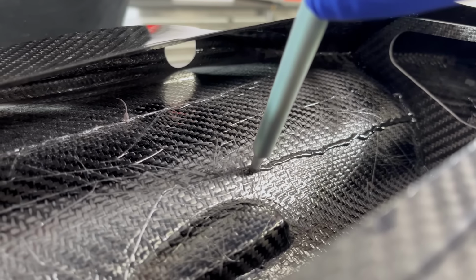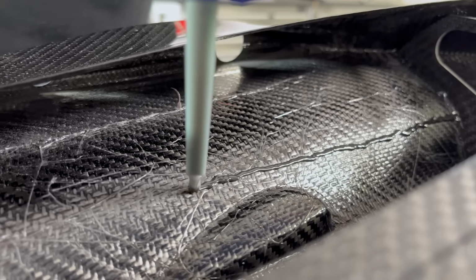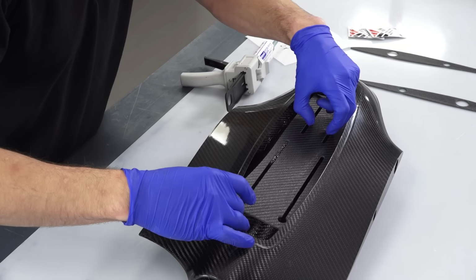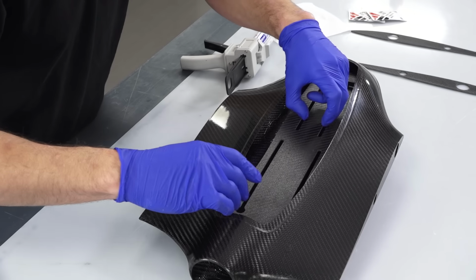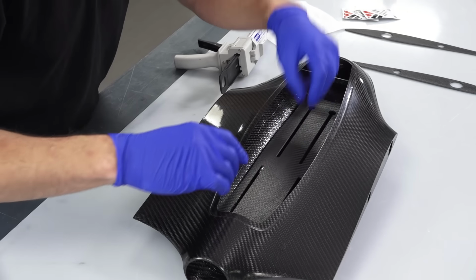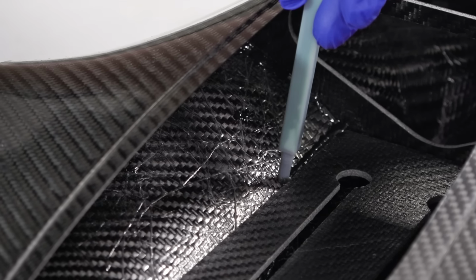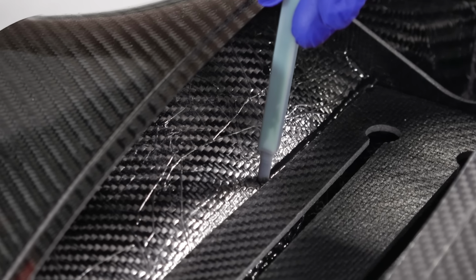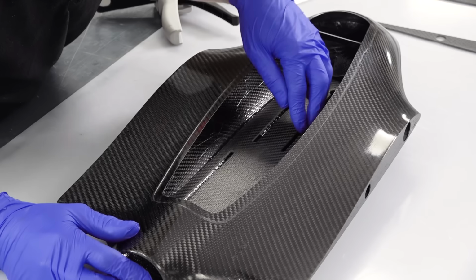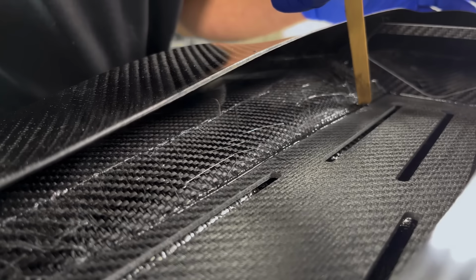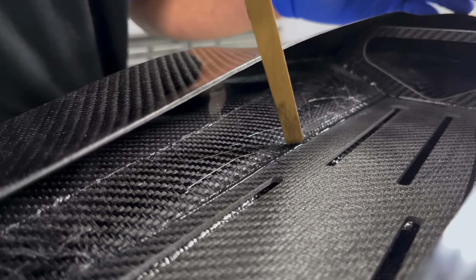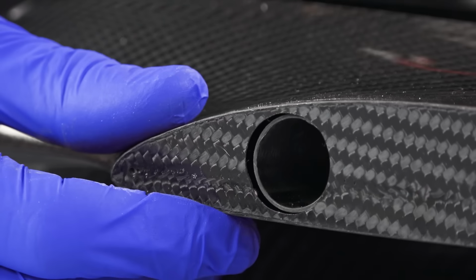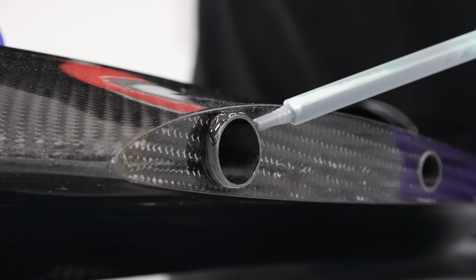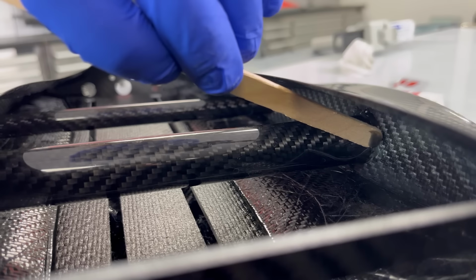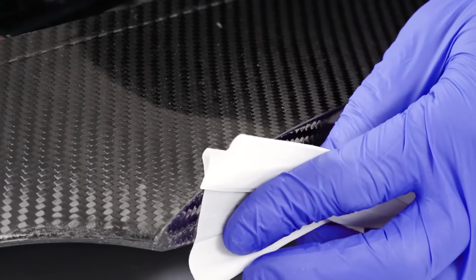This adhesive is quite thixotropic and stays nicely in place on these edges prior to the final positioning, allowing me to apply a sufficient bead to gap fill the slight texture from the bagging process on the inside of the fuselage. Wherever possible, I try to create a small fillet, as this helps to increase the contact area of the adhesive and reduces any stress concentrations. A quick run over with a lollipop stick can be really useful for this. The spar tube then receives a good bead and any excess is wiped away.